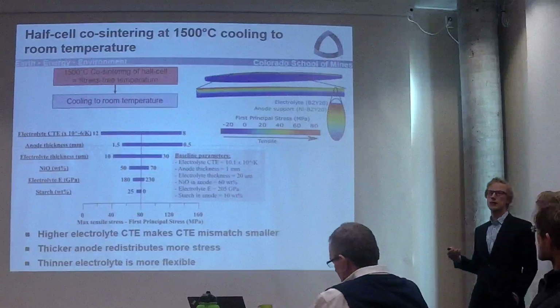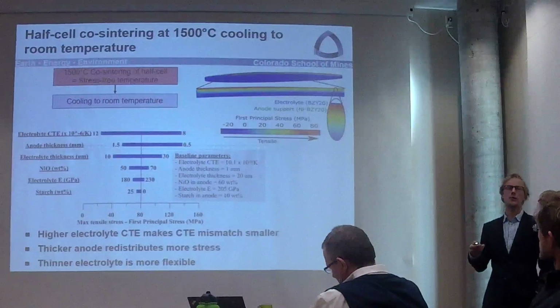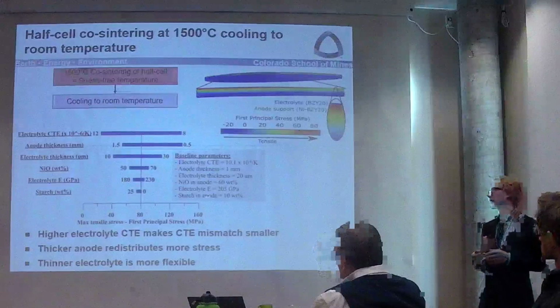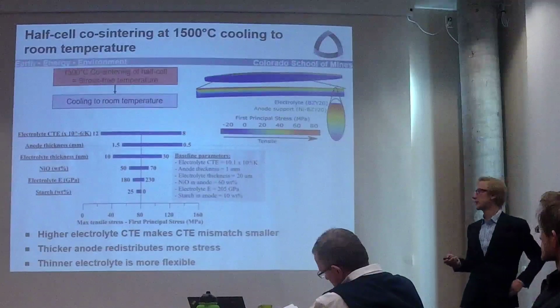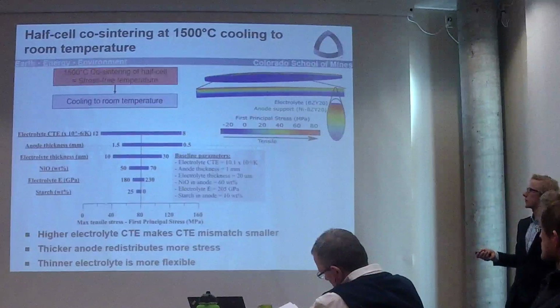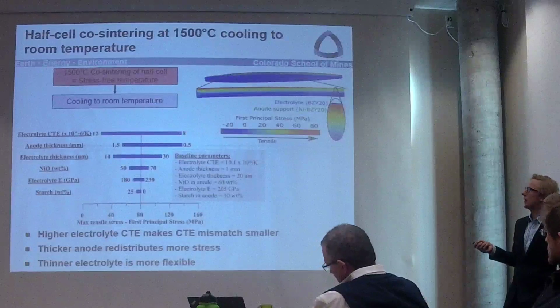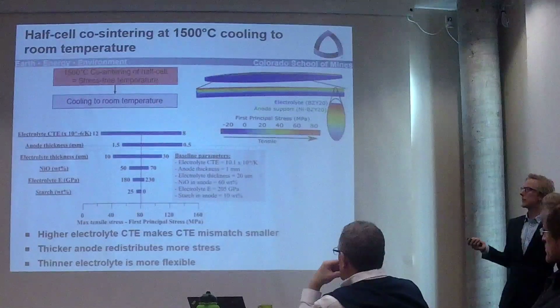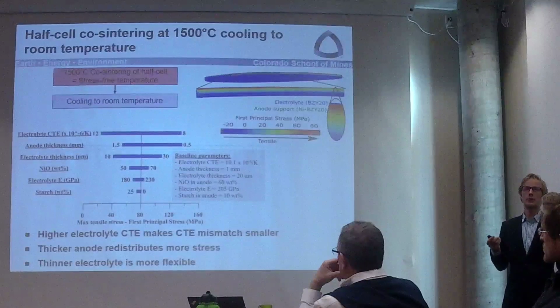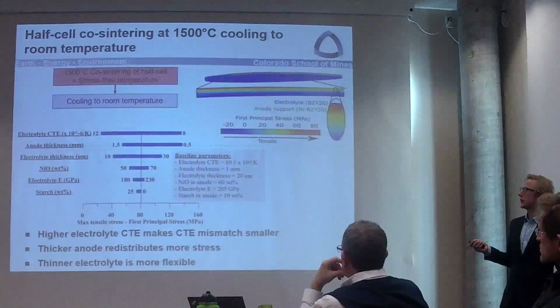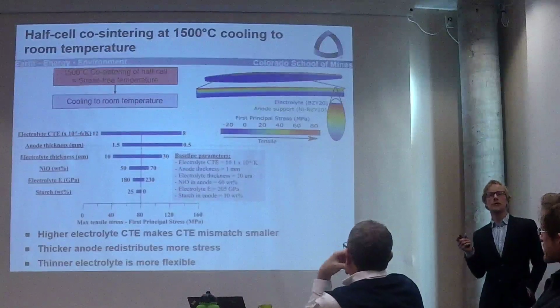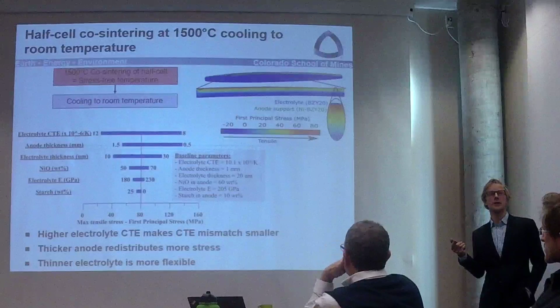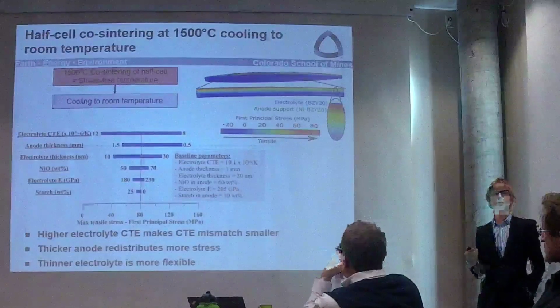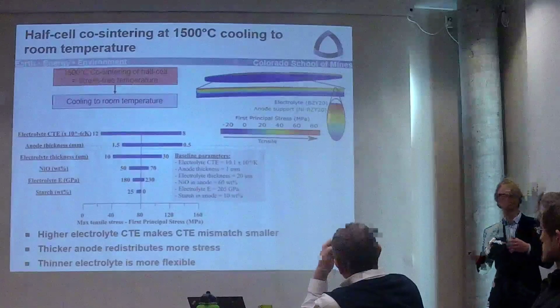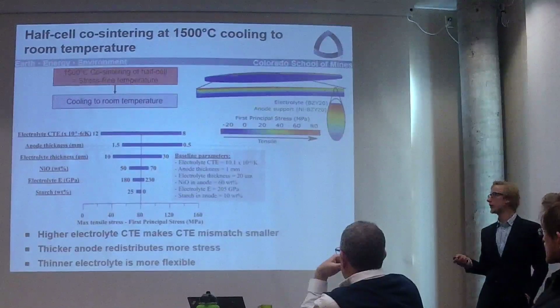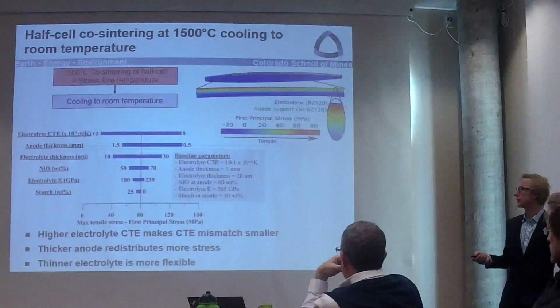So how is that maximum tensile stress going to vary, and why are we looking at the tensile? Very often they almost never break under compressive stress. And so here the maximum tensile stress is at 80 megapascal, and at the baseline the electrolyte has a CTE of 10, and so that's a pretty big difference between both CTEs. And so once you increase the CTE of the electrolyte, you decrease the CTE mismatch, and so the delta T of 1500 is going to have a much lower stress, about 20 megapascal, so that's a huge difference. Redistribute the stress over a larger amount of material and active for electrochemical performances.